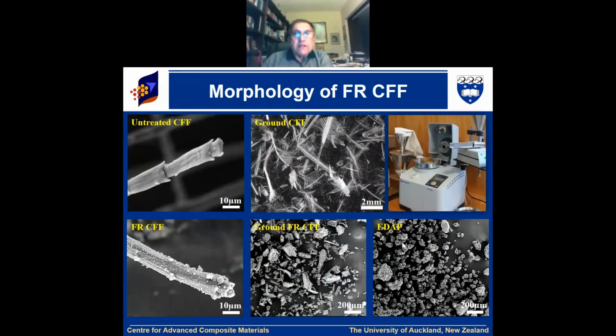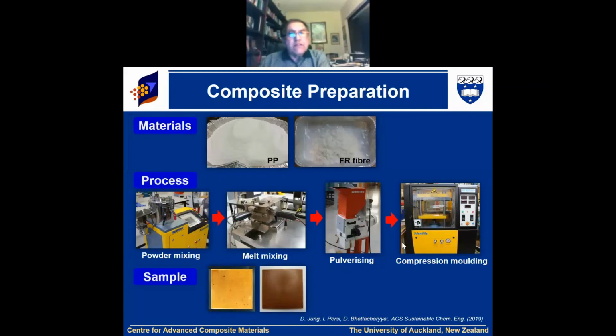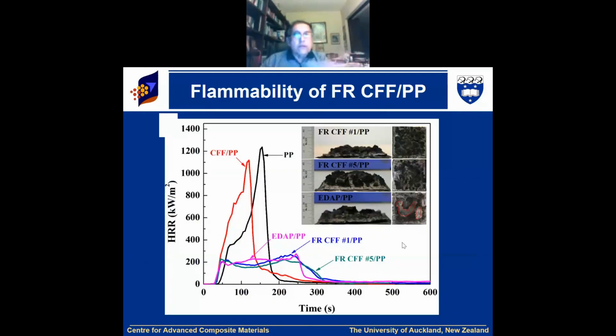So chicken feather, we used the entire thing and we mixed it just like we mixed other things, but we also got fire resistant fiber. We can keep it in fiber form. Also we pulverize deliberately so that we can mix very easily. And it was a sustainable product because the polypropylene is recyclable. FR, this chicken feather, is also a societal waste nuisance, so it was very much appreciated. And when we use that, you can see that huge drop in there, that fire resistant chicken feather, and we succeeded in this intumescent fire.